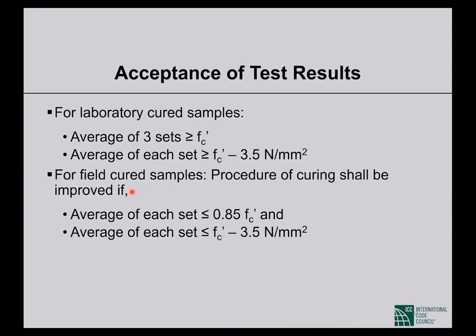But for field cured samples, where you don't send the samples to the lab, you cure them in the field until just before testing. In that case, procedure of curing shall be improved. So suppose you are getting an average of 3 sets less than 85% of fc prime, or an average of 1 set less than this, then you have to understand that your curing method is faulty. You have to improve the curing method.